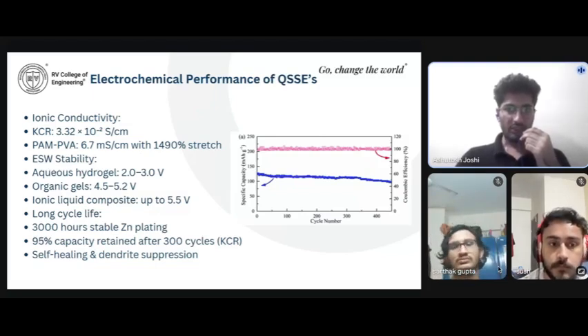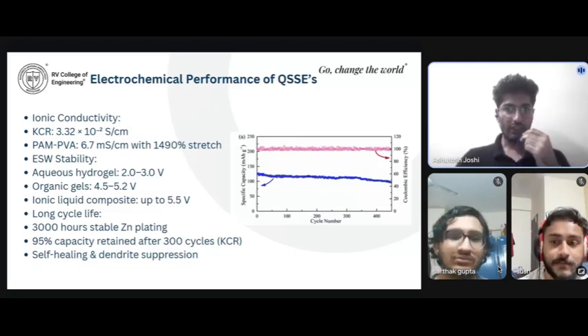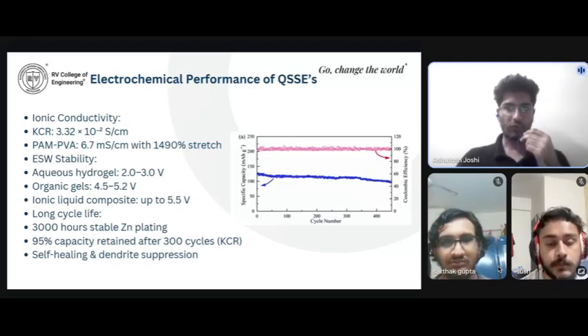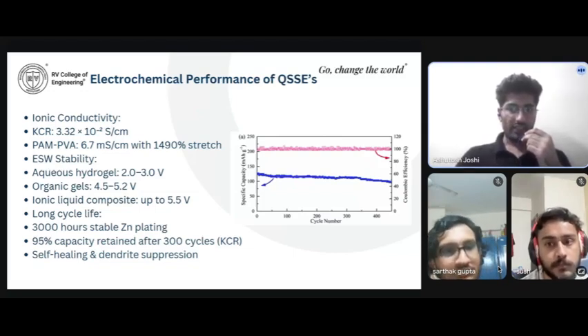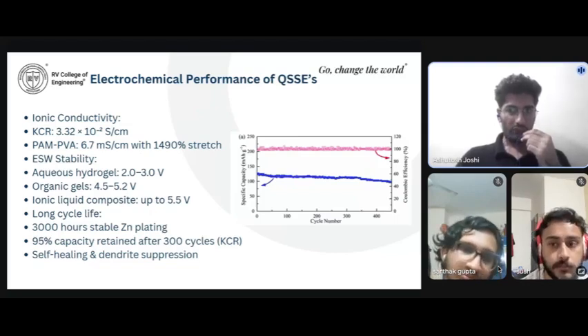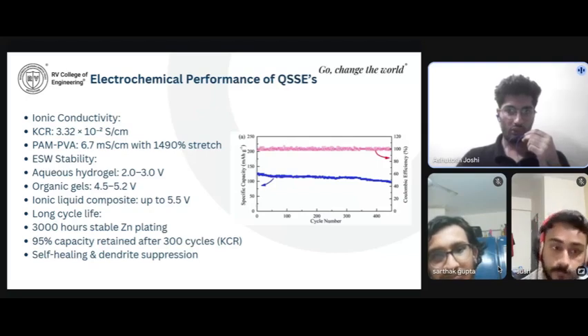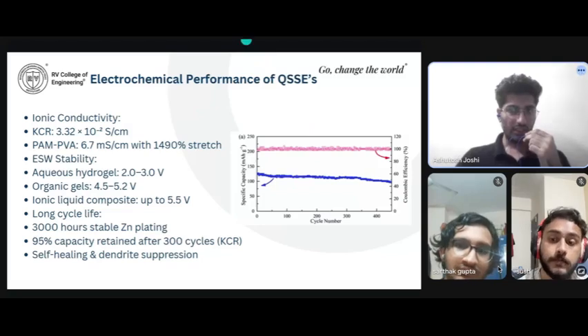Now, what the description says is about ionic conductivity. KCR-based QSSEs have a conductivity of 3.32 × 10^-2 S/cm, and PVA gels reach 6.7 mS/cm and stretch up to 1490%. Electrochemical stability windows: aqueous hydrogels have 2 to 3 volts, and organic gels have a range of 4.5 to 5.2 volts. Ionic liquid composites reach 5.5 volts, suitable for high-voltage battery chemistries.